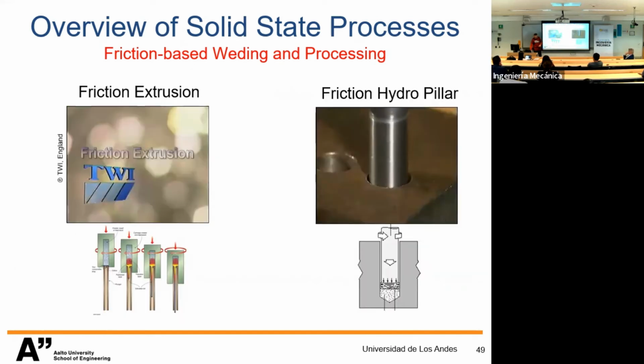I don't know why this did not start, but it starts now. So friction hydropillar processing. In fact, if you understand this process, you understand a lot about solid state. Okay? It's a maintenance technique where if you find a defect inside of a structure, of a joint or something, you drill a hole and then you fill it with material that has similar or even better properties. All this in solid state, and this is now very, very important for the area of offshore structures. Okay? So you create a viscoplasticized layer. This is rotating, and that viscoplasticized layer is going to deform the base material and create a new chemically active surface.